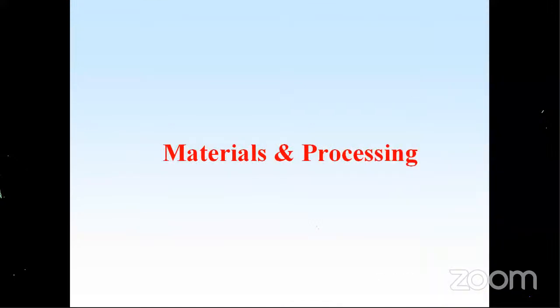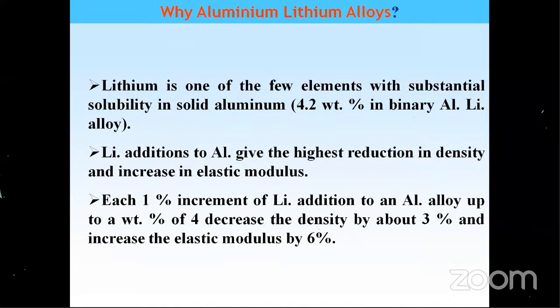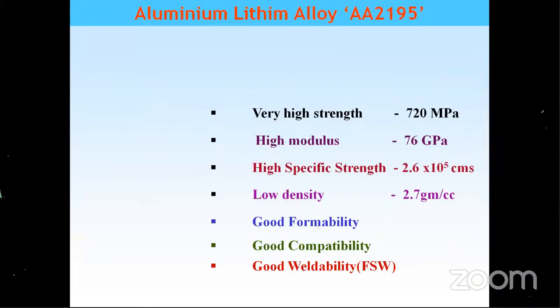In that, actually, I'll discuss some new alloys, why we should. We are also venturing into that. As I mentioned earlier, Space Shuttle actually used an aluminum lithium tank for storing liquid hydrogen and liquid oxygen. Why lithium is important is that lithium addition to aluminum gives the highest reduction in density and increases elastic modulus. For every 1% of lithium in aluminum alloy, the weight density comes down by 3% and the modulus increases by 6%. It gives very high strength, modulus, specific strength, low density, and good formability and good weldability.